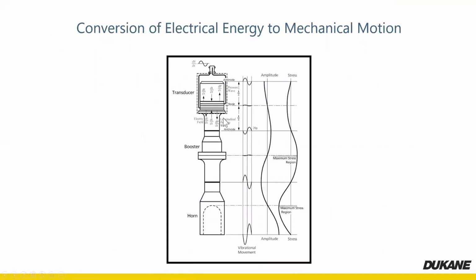So this is just another quick little slide that shows how this gain works. You see the transducer at the top with the piezoelectric ceramics. The ceramics in the transducer are the nodal point. And then we've got our antinodes, the back slug on the transducer and the front slug on the transducer, which represent the two antinodes at the very faces of them. So at the interface between the transducer and booster, you've got 20 microns of peak-to-peak amplitude at 20 kilohertz coming off of it. It's being amplified through that mechanical means of a mass above and below the nodal point. So that 20 microns, it doesn't show it in this picture, but that 20 microns is obviously getting larger. Again, let's say it's 2-to-1, you've got 40 microns here.